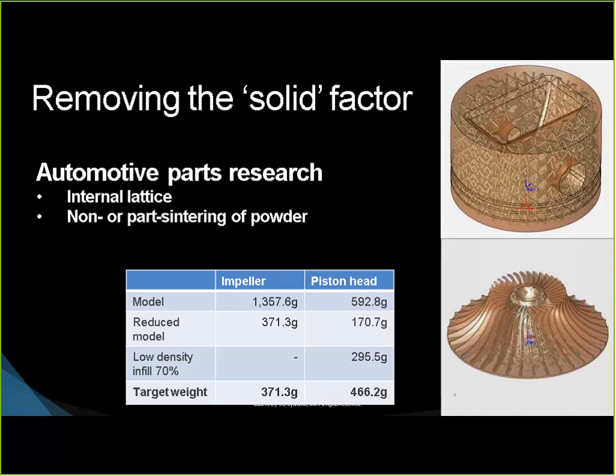In this case, what was done is we've taken a piston, what you've seen here is a piston head and an impeller. We've taken the internal components of those and replaced them with a lattice. So on the impeller section, obviously there's an area for a drain hole and there's an open space. What we've been able to do is reduce the target weight by nearly 1 kilogram. On the piston head, however, just to avoid post-operations and post-welding, we were still able to reduce part weight by some 20 to 30% by filling with lattice and then leaving that powdered infill. It's roughly about 70% of the density of the melted powder.